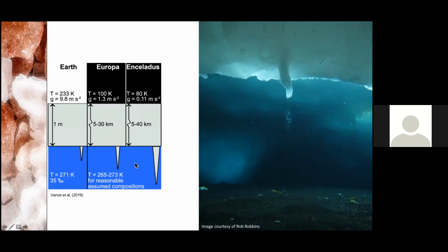So this is provoked by the salting out effect, which is also known as the salt-induced crystallization or salt fractionation. And it produces a concentration of the brine, which is denser and has lower freezing point than the surrounding water. So the formation of clathrates accentuates the salting out effect because the CO2 competes savagely against the salt.